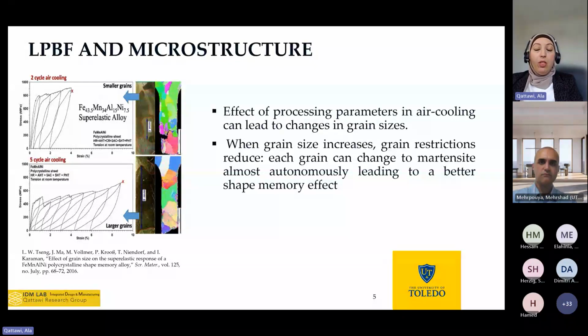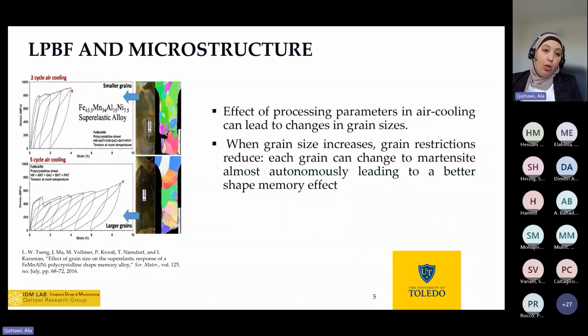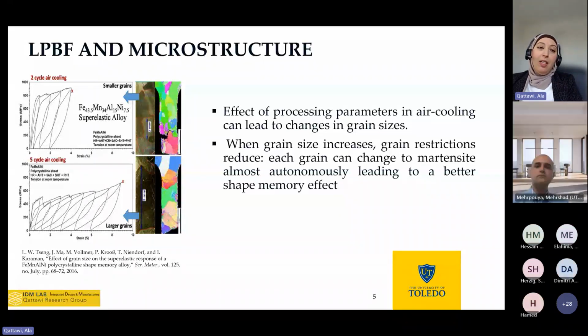So what we can understand is that the cooling rate, for example, the thermal changes across the process when we manufacture this part, can change the grain structure. And this can significantly affect the performance and the super elasticity that we can get from this alloy system. So potentially, what we're saying is that this alloy system has potential. It can show better strain recovery and less dependency of the critical stress on temperature. And if we understand the process parameters carefully, then we can design this alloy system and structure in order to get the needed properties.